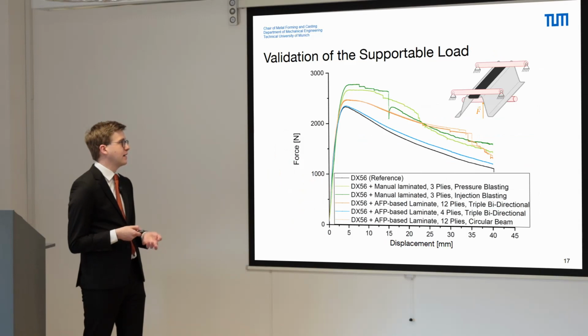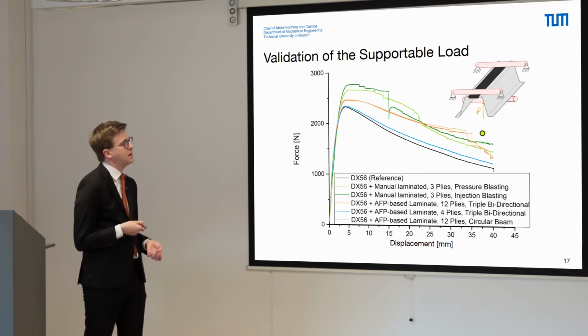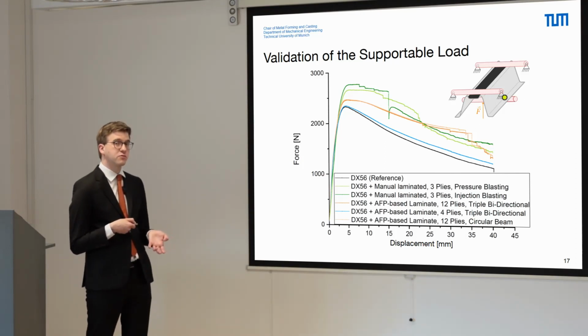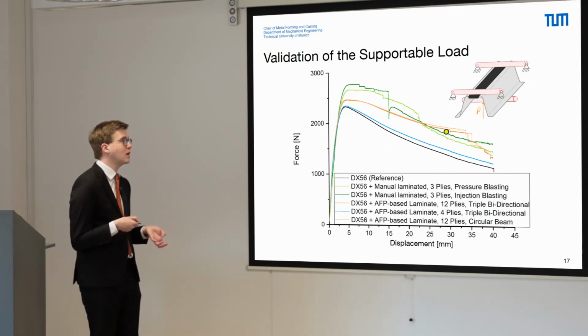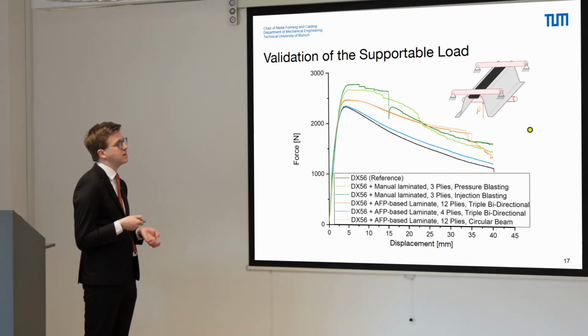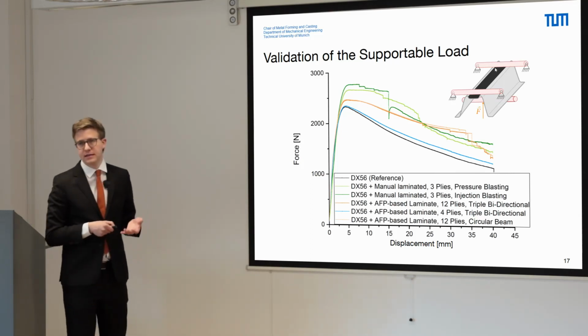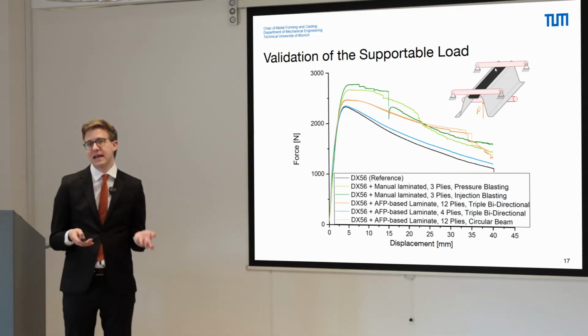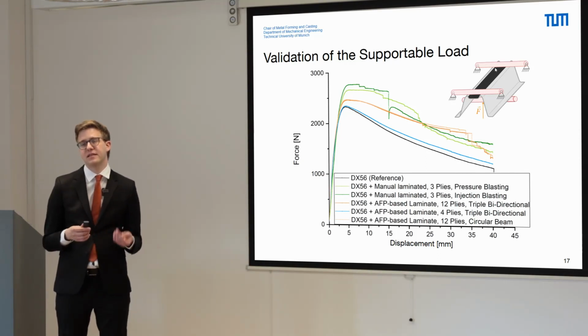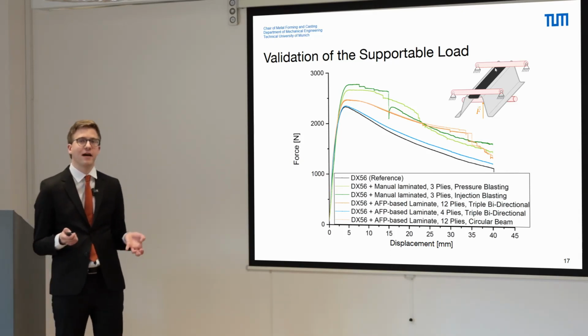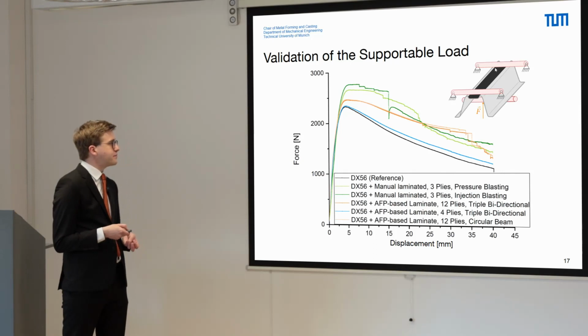Therefore, in the next experimental investigation, we performed three-point bending tests on the hybrid bead geometry itself, and we only analyzed the configuration where the UD fibers are subjected to tensile load. It arises as a design guideline for static load cases that the beads must be aligned in such a way that the UD layer is subjected to the tensile load case.